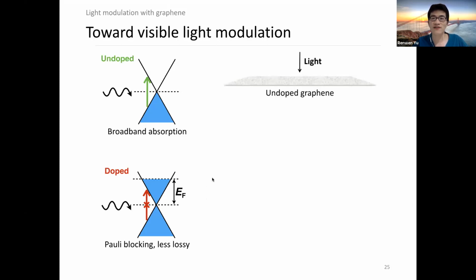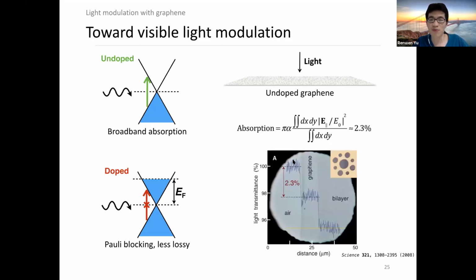When an external light is impinging onto an undoped graphene film, we can calculate its absorption by this formula, where alpha is again the fine structure constant, and we can find the well-known 2.3% light absorption in a broad wavelength range. This broadband light absorption has also been observed experimentally. So even with this effect, it can only provide a very small amount of absorption. In order to boost the light absorption as well as the light modulation, one can think of increasing the field enhancement at the graphene plane.